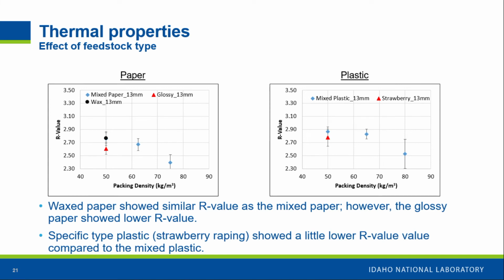So when we tested whether the different fractions of the paper or plastic have an effect or not, we saw it depends on the fraction type. For example, we saw that the glossy paper had less R value, which most likely reminds us that glossy paper has higher conductivity than other paper. That's why we saw less R value on that paper. But in plastic, we didn't see that much change in the R value with the different types of plastic.